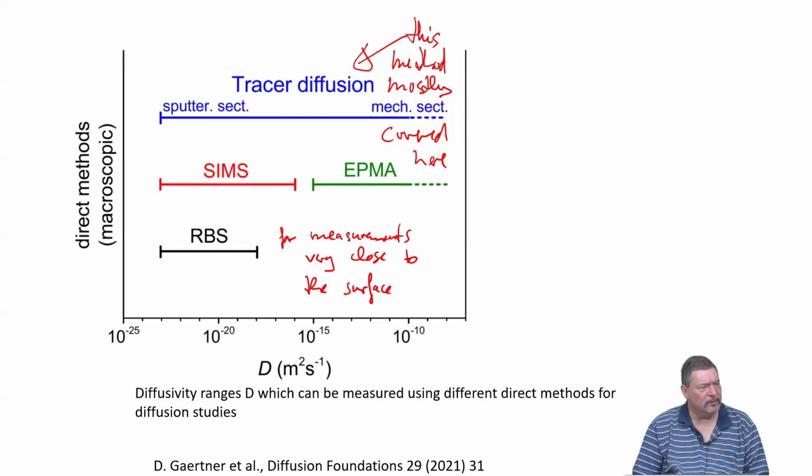A good radioactive tracer needs to have a half-lifetime which is sufficiently long so that we can apply it, go through all the steps I'm going to show you in a minute, and in the end still have enough tracer left in the material so the detector can still count the decays. So if you have only, let's say, a lifetime of half an hour, after half an hour, half of the applied tracer will be gone. It's not longer radioactive. And after another half hour, again, half of the half is gone, right? So you have left only 1/4.